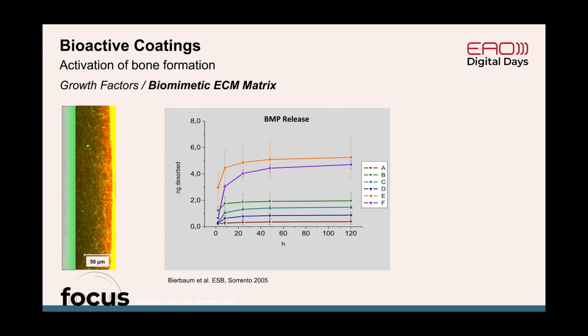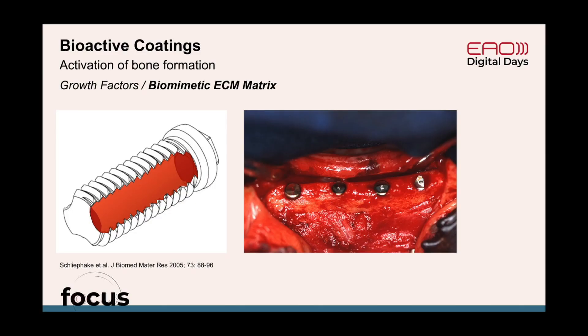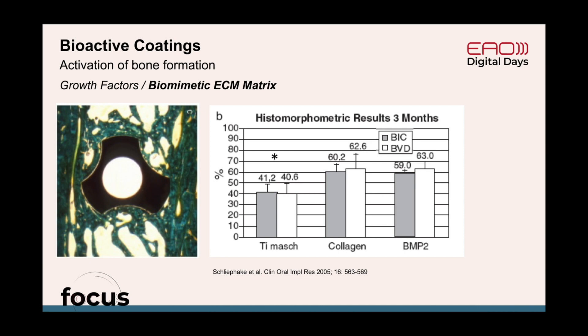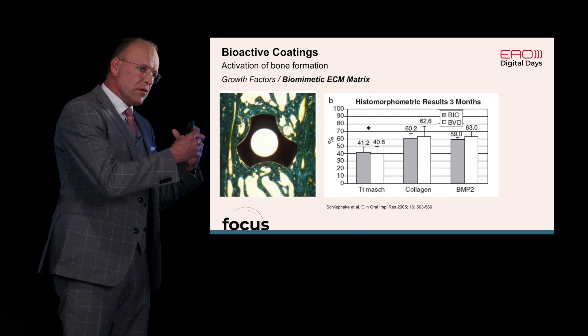We then went into a preclinical trial using the dog model with screw implants with excavations to allow for bone ingrowth and evaluation of bone formation. When we compared titanium machined surfaces, collagen surfaces, and the BMP surface, we could see that machined titanium and collagen were significantly different, with significantly lower values on the machined titanium surface. However, the BMP surface was not able to additionally improve bone implant contact or bone density. The reason may be that the amount of BMP spontaneously adsorbed to this extracellular matrix coating, and the amount released — only four to five nanograms — was probably too low.